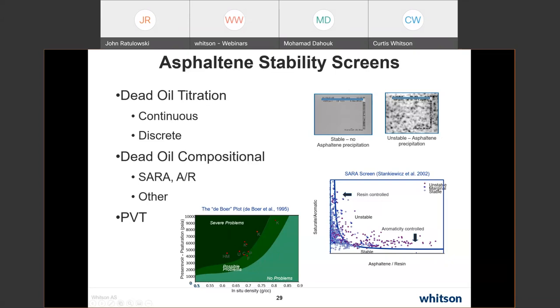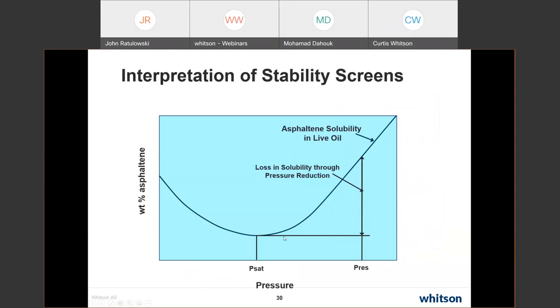And so I made a little cartoon of that, and that's what comes up next. This is a solubility trace for asphaltene as a function of pressure at a given temperature. So the asphaltene solubility in live oil, as I decrease the pressure, and we talked about this, will decrease until I get to the saturation pressure. So as I go down below the saturation pressure, it comes back up because I'm liberating gas from the system. So the actual remaining liquid phase is a better solvent. So the loss in stability through pressure reduction is this right here. This is related to the compressibility of the system and the gas content of the system.